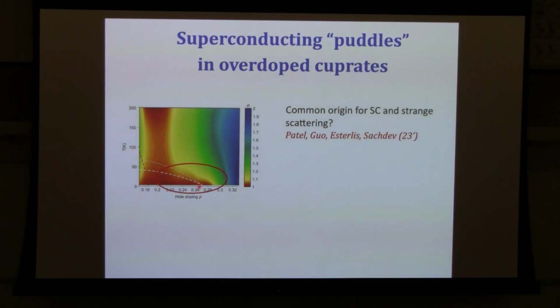However, because of disorder, because of inhomogeneity, there's what's called the Griffiths phenomena. Some regions of the sample actually look like they're already in the ordered phase, already on this side. So there's this plethora of low energy spin fluctuations that are causing the strange metallic scattering over this entire regime. And it's the same spin fluctuations that would also cause the pairing, and hence the correlation between strange metallic behavior and superconductivity.